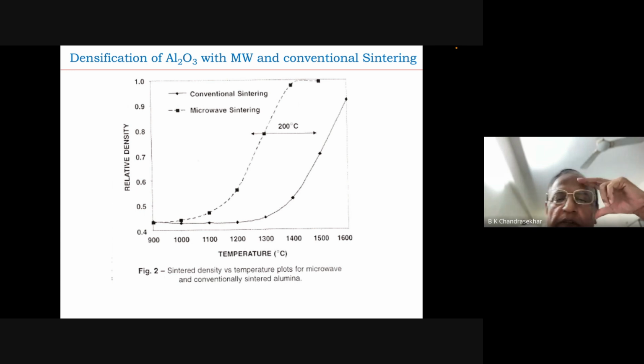Now let us look at the sintering of aluminum oxide with conventional sintering and microwave sintering. We talked about this in the previous talk. Basically, you start with a very sub-micron size aluminum oxide powder - sub-micron meaning the average particle size would be of the order of 0.5 or 0.6 micrometers.